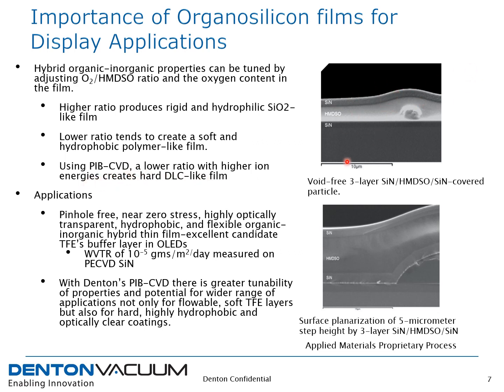And this is the work done at Applied Materials, where they show PECVD coated multilayers consisting of silicon nitride, plasma polymerized HMDSO buffer, and silicon nitride structure for flexible mobile device applications. They show a flowable buffer film that can cover a particle without leaving any voids or diffusion channels around it. And here they show a non-conformal step profile leading to planarization of surface irregularities.